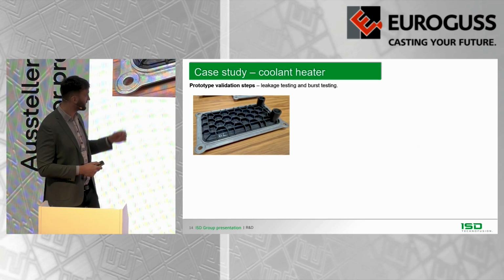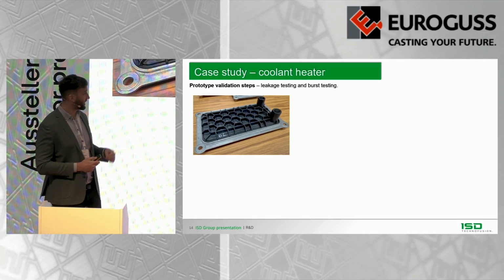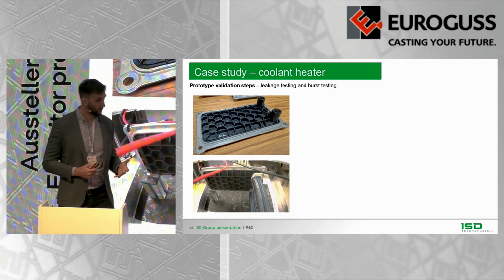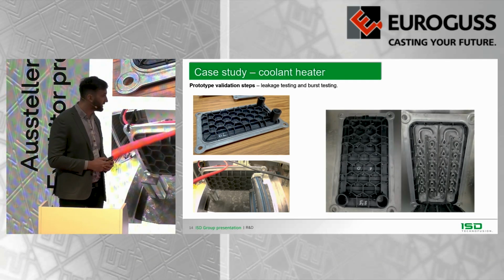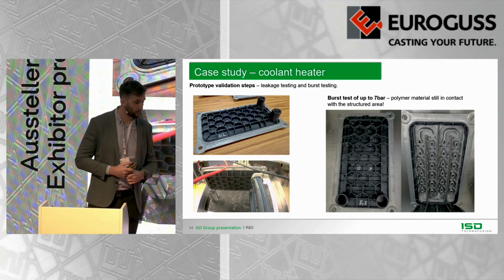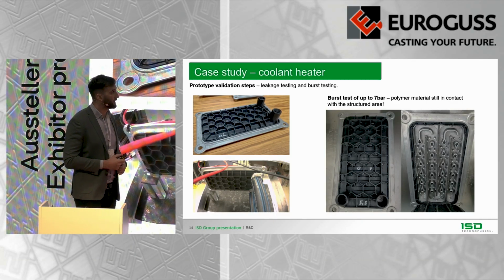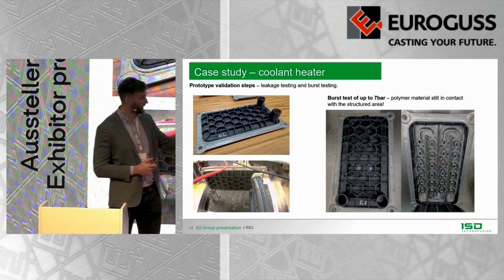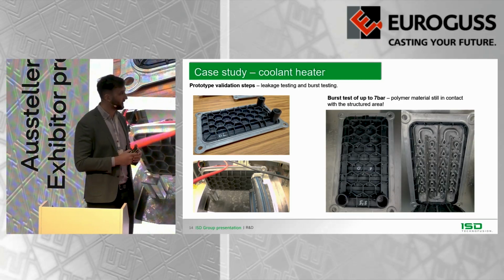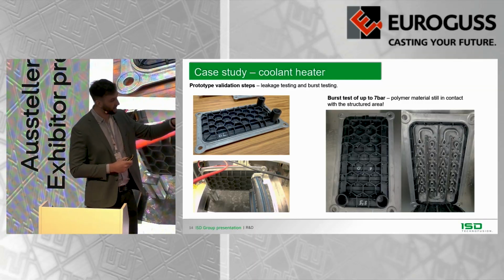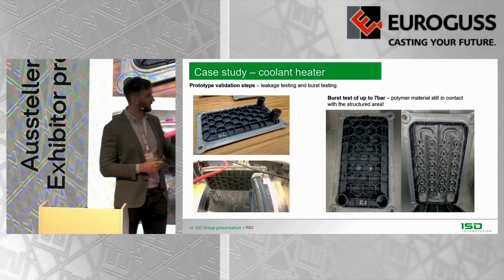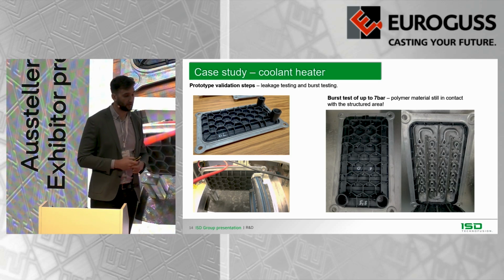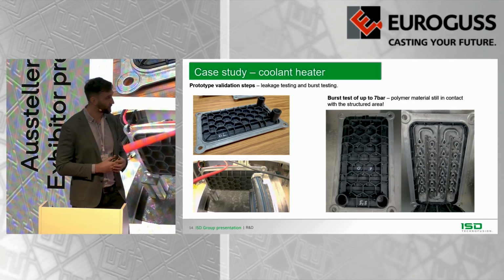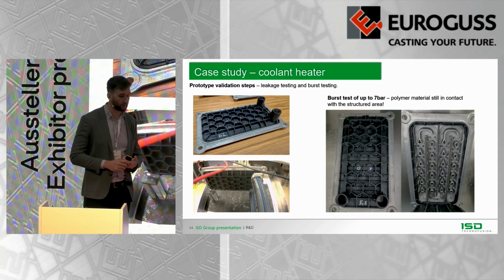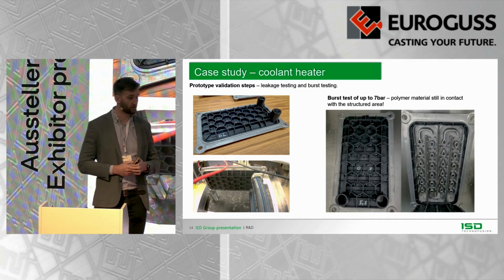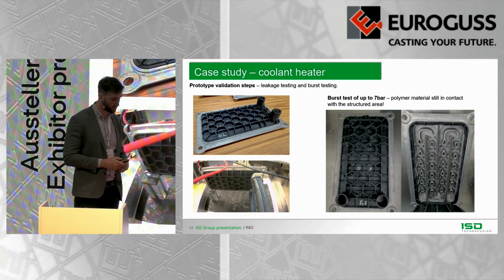So this is one of the first prototypes that we produced. You can also check it out at our booth. We're right now also doing burst pressure tests and fatigue tests. As you can see, we've been able to reach up to 7 bars of burst pressure. And I think the most important point here is that the welded area, or the area that is structured, was stronger than the polymer itself, because you can see that the polymer cover at the burst test broke around the welding area. So the weld itself withstood the required pressures. So 7 bars, I think, is more than enough, because the majority of applications in active thermal management will be around 2 to 3 bars, depending on the use case of the customer.